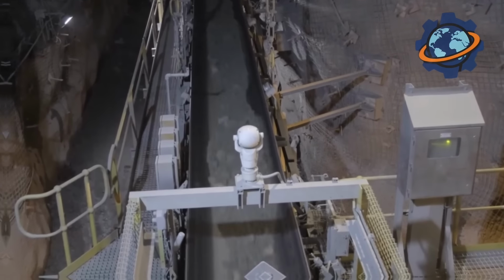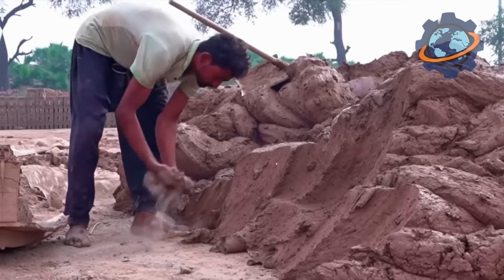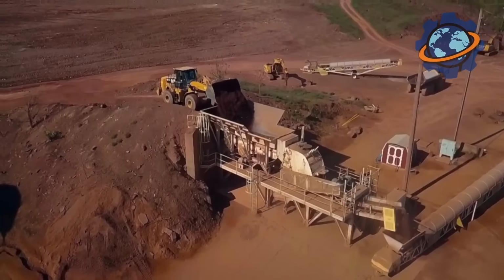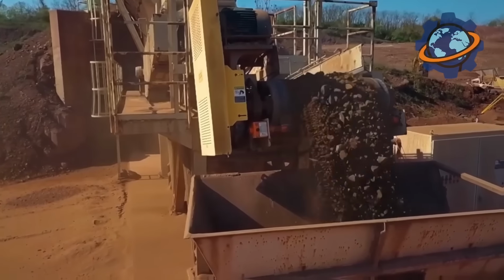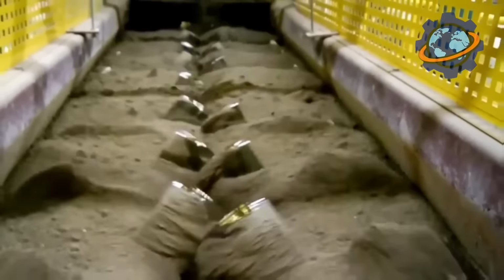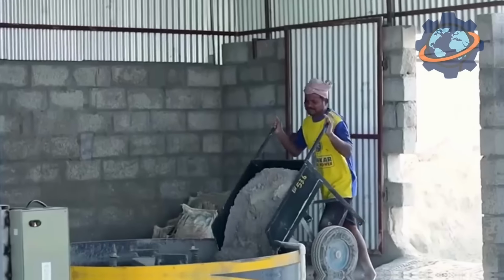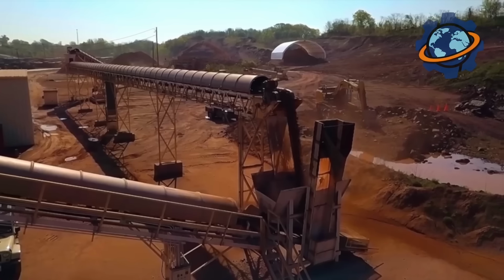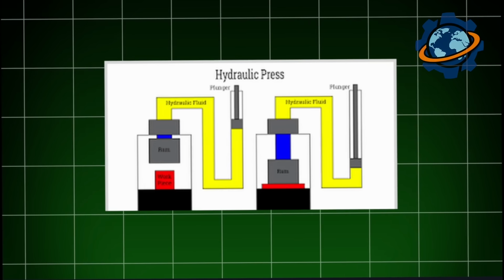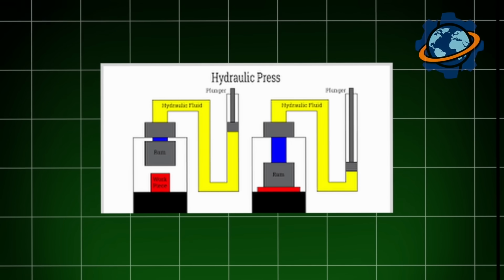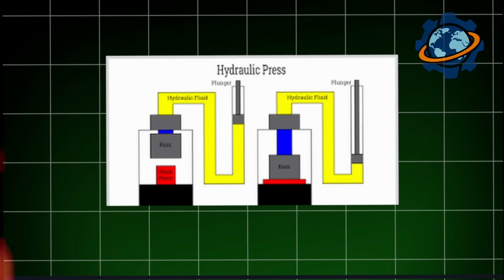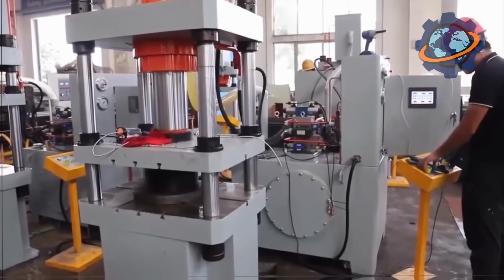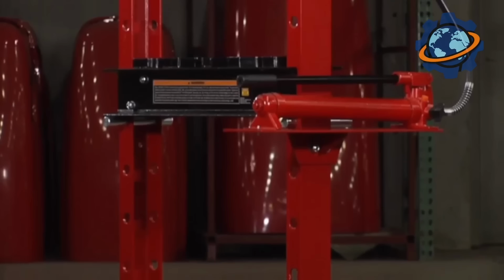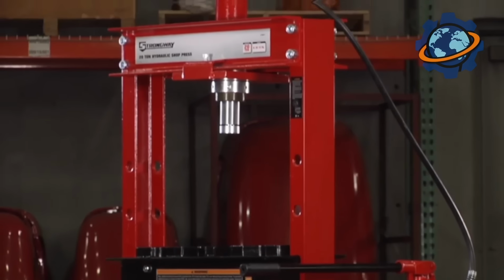The mixing drums rotate for 40 minutes. Technicians pull samples constantly, checking consistency. The mixture emerges as damp, grainy paste. Looks like chunky peanut butter, but feels like dense sand. This strange hybrid contains both the dead and the living, the fired and the raw, the stable and the flexible. Hydraulic presses generate forces exceeding 2,000 tons, compressing the clay chamote mixture into brick shapes. The pressure is critical. It determines density, which determines strength.